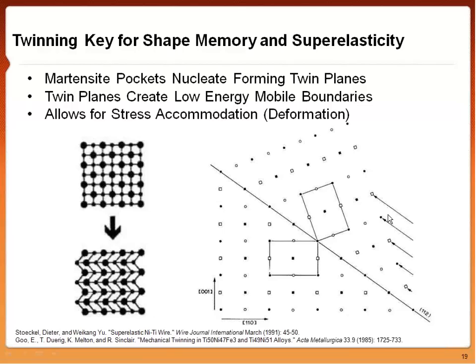You can see that these low energy boundaries parallel to the twin plane are very mobile, and so when stress is applied to them, they accommodate it very well, instead of some of the conventional things you think of as slip and more dislocations forming. So in effect, when the stress is applied, the boundaries are slightly sheared in this example of a 2D projection, and allows for an easy accommodation of stress and not actually breaking material.